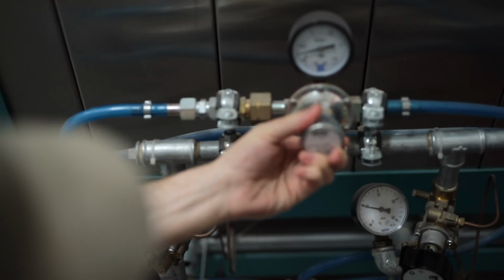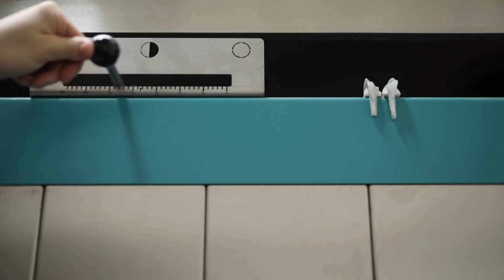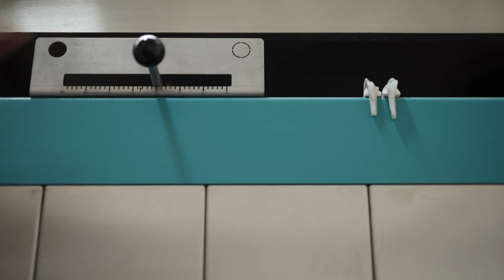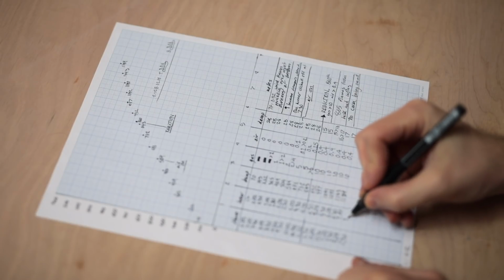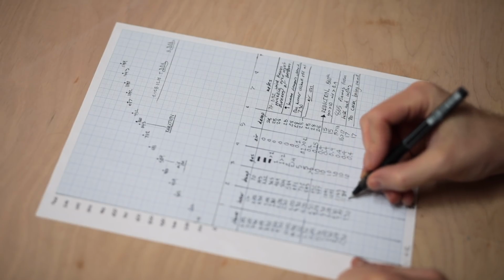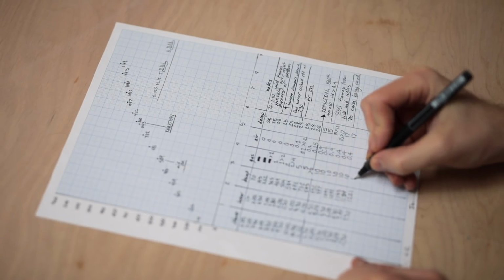I also close the dampers, which cover the flues of the kiln, to about halfway. This puts the kiln into a reduced state, which means the internal atmosphere is burning with insufficient oxygen, and as the gas inside combusts, it does so inefficiently and seeks more oxygen, which it ends up finding from within the clay and glazes of the pots themselves, and thus changes their colour. After I've initiated this atmosphere, the temperature begins to climb a bit more slowly, and as it increases, the flames that protrude from the kiln become brighter and stronger.